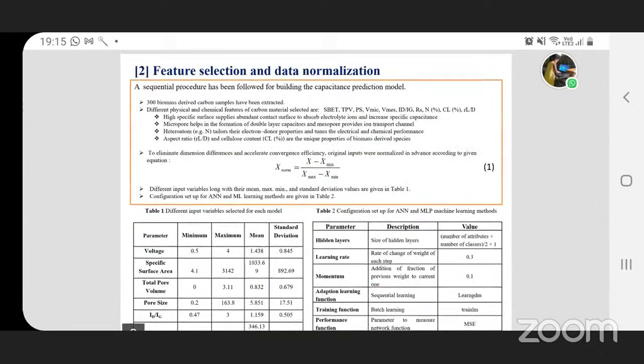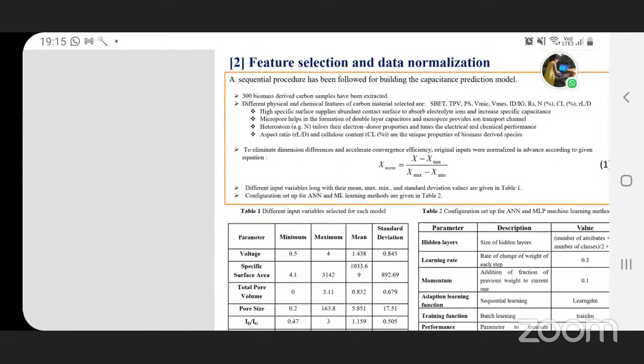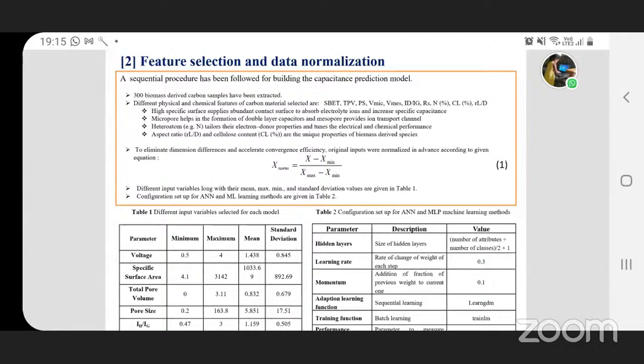Okay. So for my computational analysis, I have taken a total of 300 biomass-derived carbon samples, and I have selected a total of 10 parameters which are going to affect the specific capacitance as well as the energy density of the biomass-derived materials. For the parameters, I have considered the surface area, total pore volume, pore size, micropore volume, mesopore volume, the intensity of D by G ratio, internal resistance, nitrogen percentage.